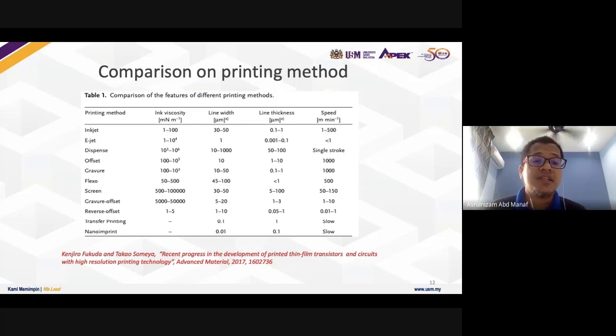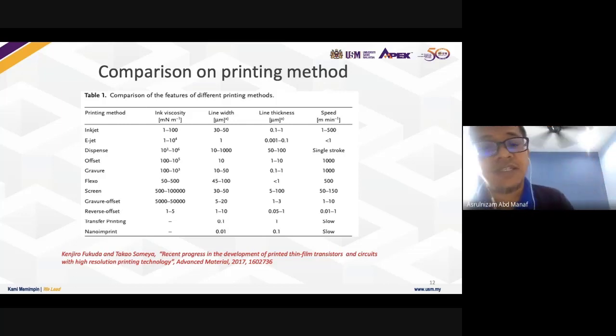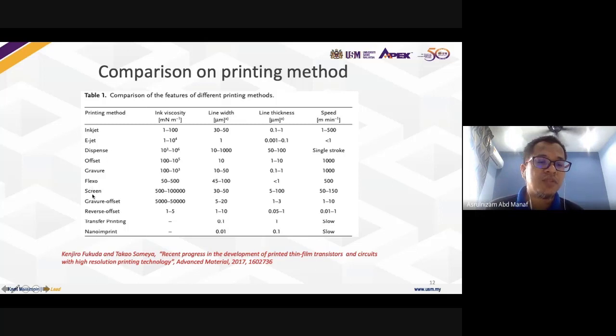right? So in my group, generally we have two types of printers that we focus on: the inkjet, and also screen printing. I mean, to start the explorations in our printable electronics. So why inkjet? If you compare to screen printing, with inkjet you can minimize the ink, which means you can avoid waste. But it is very challenging. From our experience, I work with a few groups on ink formulation. It is very challenging to do the ink formulation for inkjet-based printing, compared to screen printing.